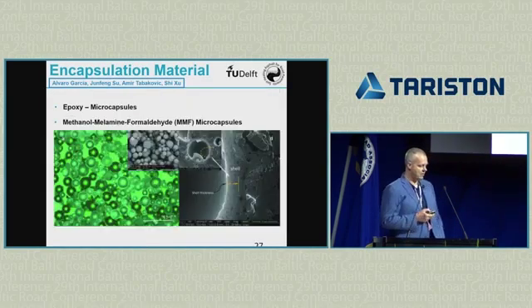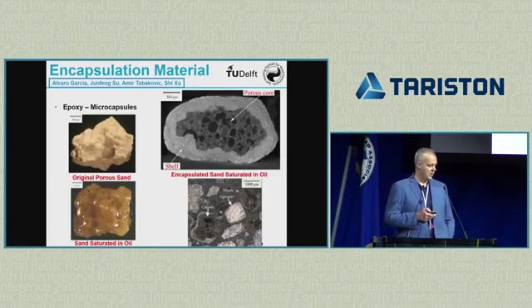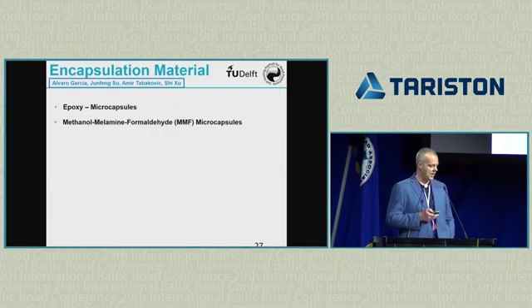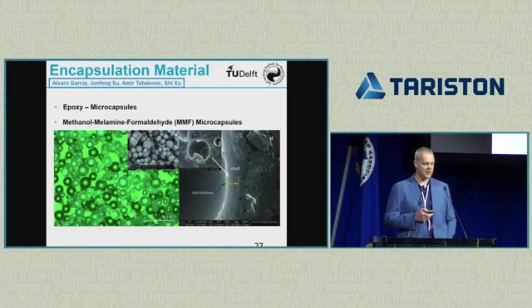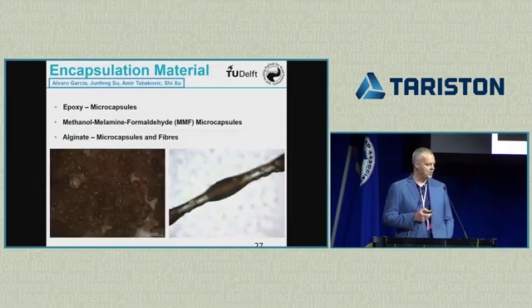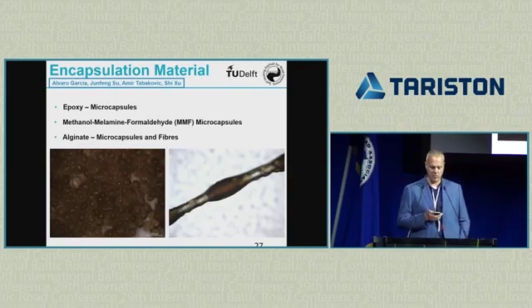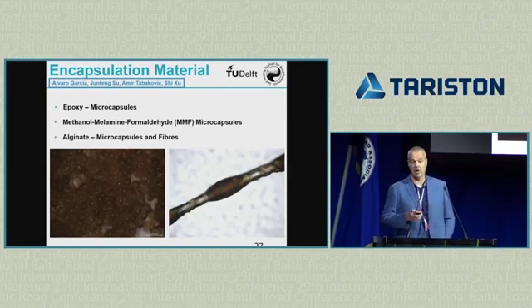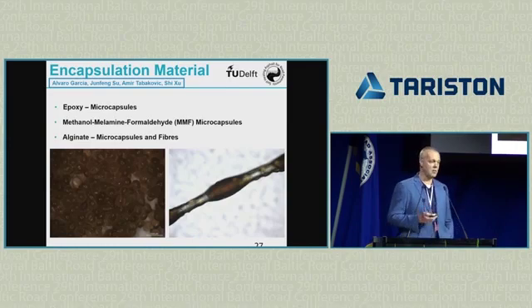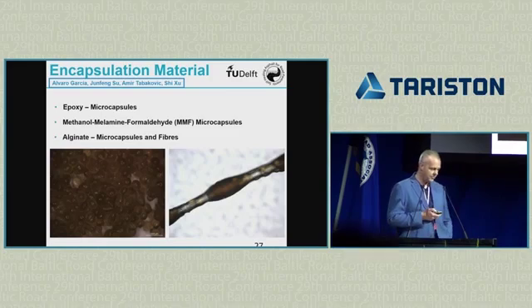We made different capsules, bigger ones, millimeter size. We made very small ones. And now we are working on alginate capsules where the rejuvenator is inside, and these actually work quite nice because they survive the mixing, they survive the high temperatures, and they break when they are needed. And we also can put them in fibers so that you make fiber-like capsules with pockets of rejuvenator inside.